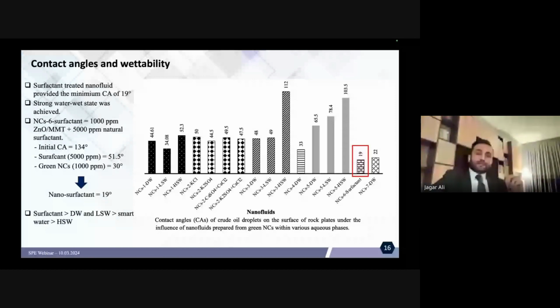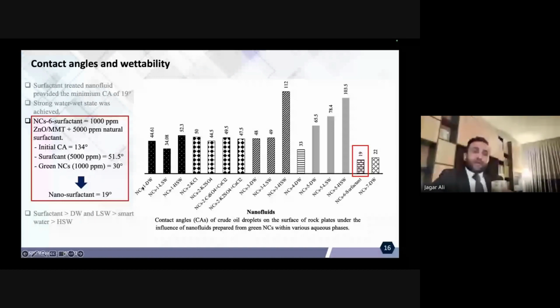So for contact angle, the minimum contact angle that was achieved in this project was 19 degrees, which is very low. When you have 19 degrees, it means the rock and the porous media is strongly water wet. So with a strong water wet system, oil is free to be moved and it can be easily produced. This was achieved when nanocomposite number 6, which is ZnO/montmorillonite (MMT), was mixed with 5,000 ppm of natural surfactant. Okay, so the initial contact angle was reported to be 134 degrees, and then by injecting surfactant, it was reduced to 51.5.